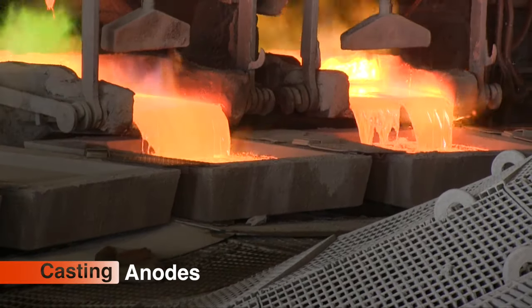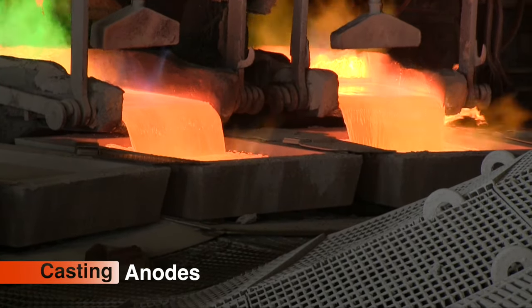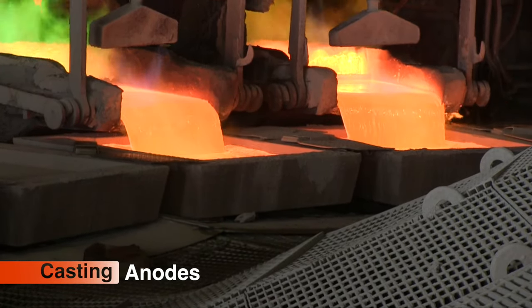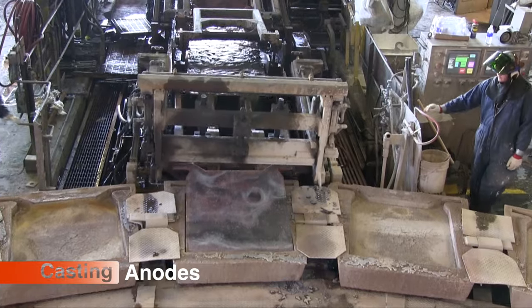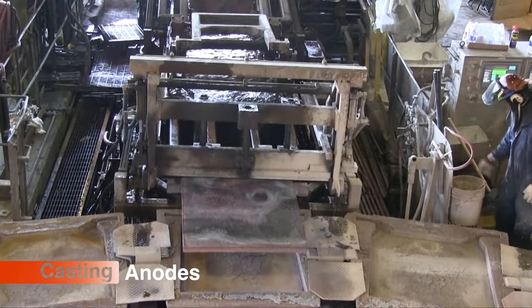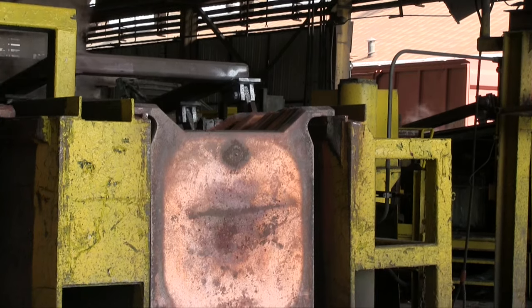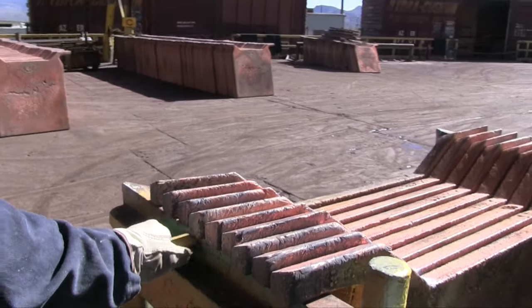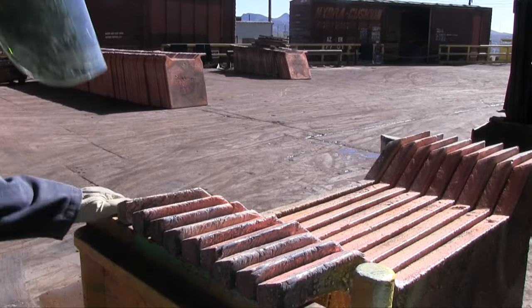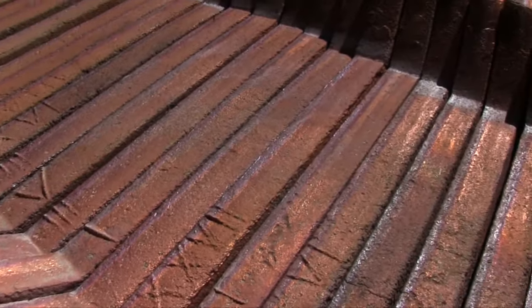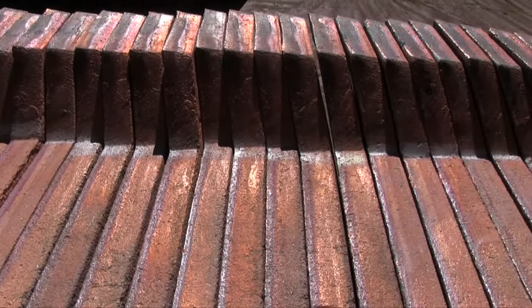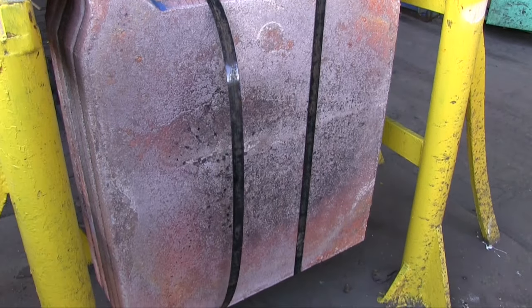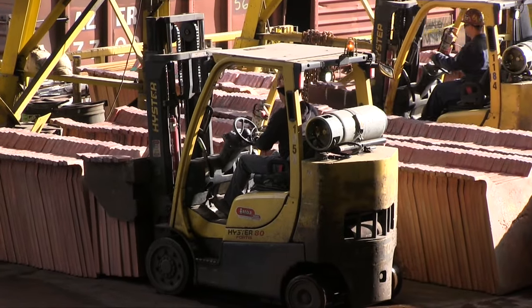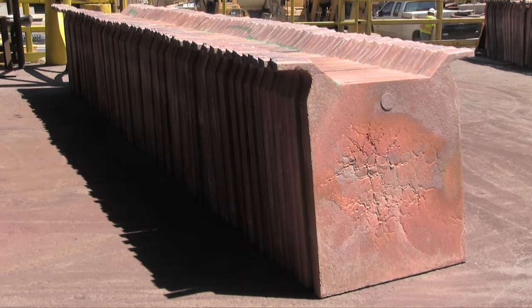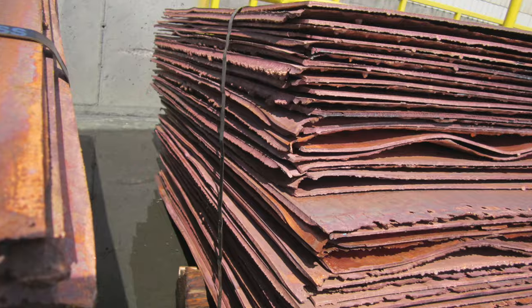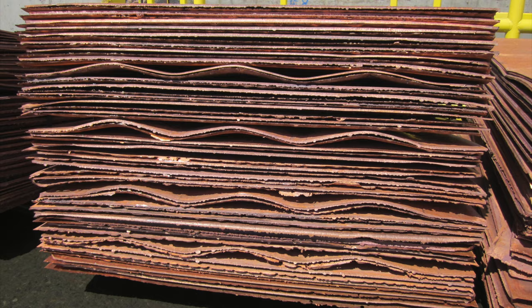In the casting phase, we pour the molten copper into molds arranged on a large rotating wheel. The copper cools and solidifies to form slabs called anodes. Weighing 855 pounds each, anodes are the smelter's final product. We apply strict quality standards and transport them by rail to our electrolytic refinery in El Paso, Texas. Refining the anodes produces copper cathodes of at least 99.9% purity.